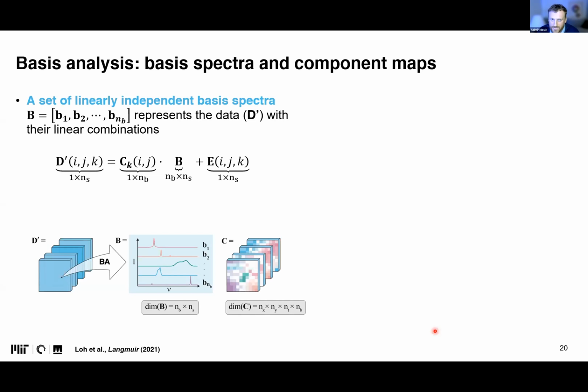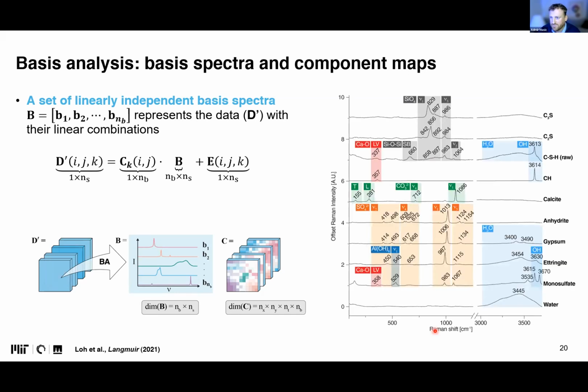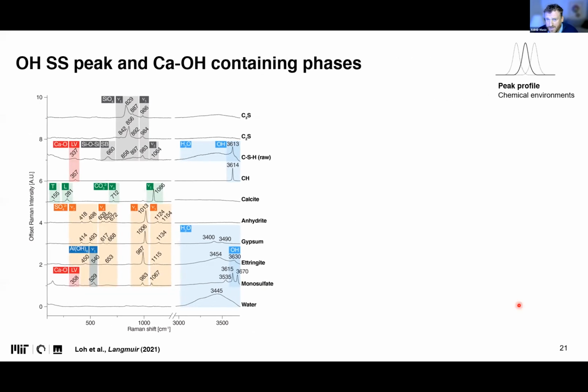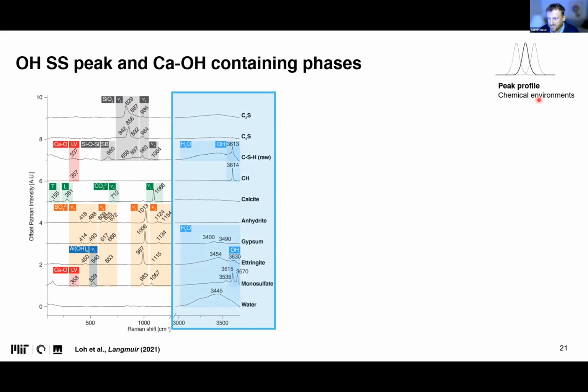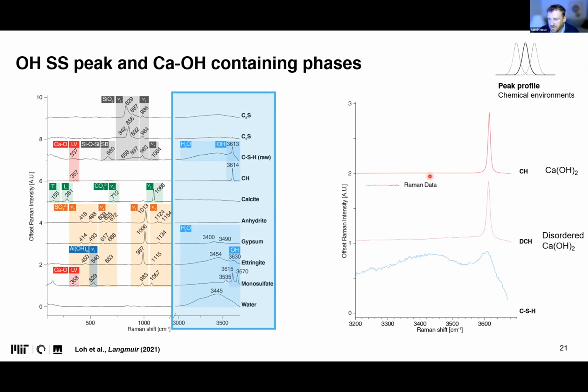So here we can post-process these cubes and get basis spectra, which would look something like this, and each of these has specific characteristic peaks of molecular unit vibrations that give us that fingerprint for each of these molecules, including water, of course. So we can then focus and look at the peak profile, for example for chemical environments. As I mentioned before, peak position and shape will inform on the environment. If we focus here on our spectrum of CSH, I like that, and also CH, calcium hydroxide,